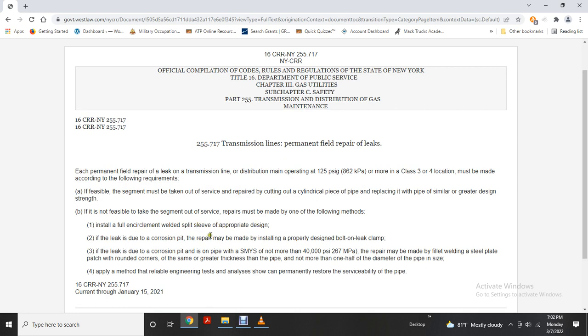If the leak is due to corrosion pitting, the repair may be made by installing a properly designed bolt-on leak clamp. If the leak is due to a corrosion pit on pipe whose specified minimum yield strength is not more than 40,000 psi, the repair may be made by fillet welding a steel plate patch with rounded corners, of the same or greater thickness than the pipe and not more than one-half the diameter of the pipe in size. Or, apply a method that reliable engineering tests and analyses show will permanently restore the serviceability of the pipe.